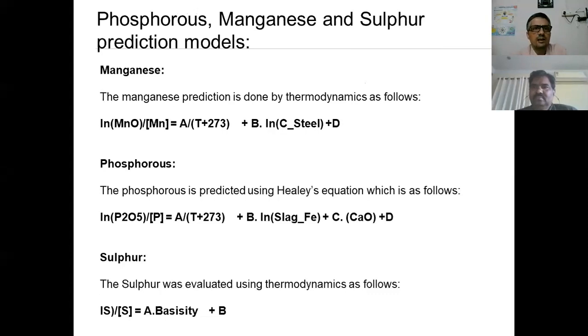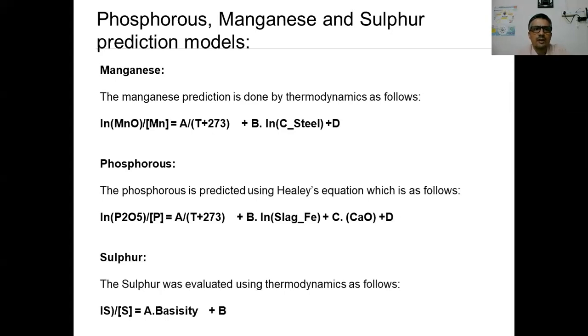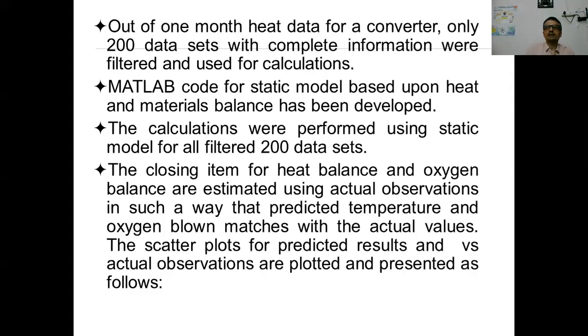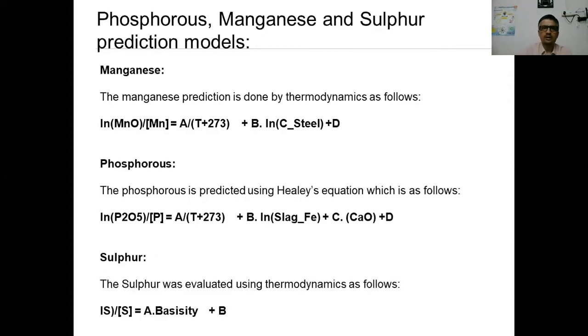As far as the distribution of manganese, phosphorus, and sulfur between the metal and slag is concerned, we can use thermodynamically derived, similar kinds of equations. For example, for phosphorus, Healy's equation has been used. For sulfur, we know that it is a function of basicity. Manganese distribution is a function of carbon. So all the equations have been incorporated into the model. And then from the steel plant we have collected the data, because once we have developed the model, unless we validate it with the steel plant data, it is of no use actually.